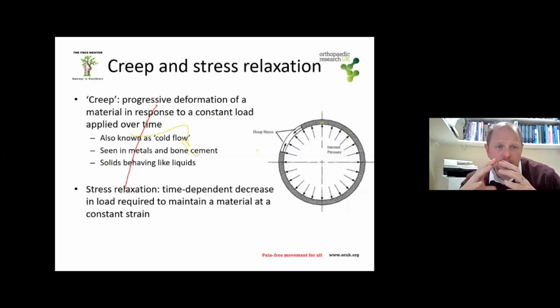And that means that if you're hitting your acetabular cup in and you're hitting it really hard and fast, but not giving time for the hoop stresses that are building up in the acetabulum to dissipate, then you can get a fracture. I've seen that with intramedullary nails going down a slightly unreamed isthmus of a bone. If you hit it too hard and fast, you're not giving time for the bone to relax, and as a consequence, you can end up with fractures because you're not allowing stress relaxation to occur.